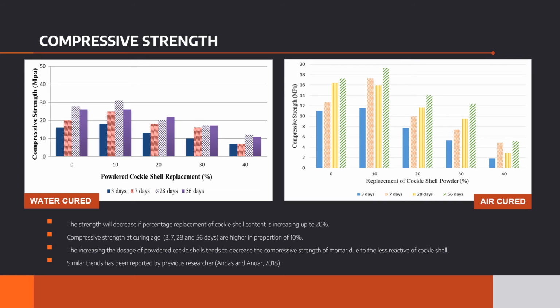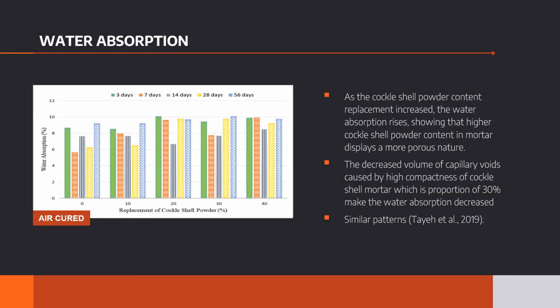Compressive strength for all curing ages is higher at the proportion of 10%, but the strength will decrease if the percentage replacement of cockle shell content is increased up to 20%. The increasing dosage of powdered cockle shell tends to decrease the compressive strength of mortar due to the less reactive nature of cockle shell. For water absorption, as the cockle shell powder content replacement is increased, the water absorption rises, showing that higher cockle shell powder content in mortar displays a more porous nature.